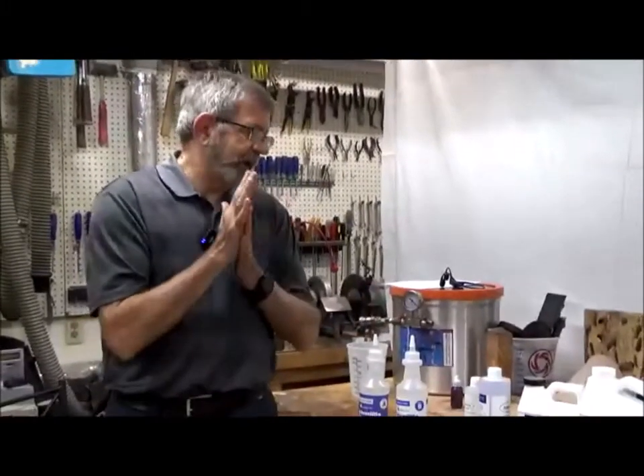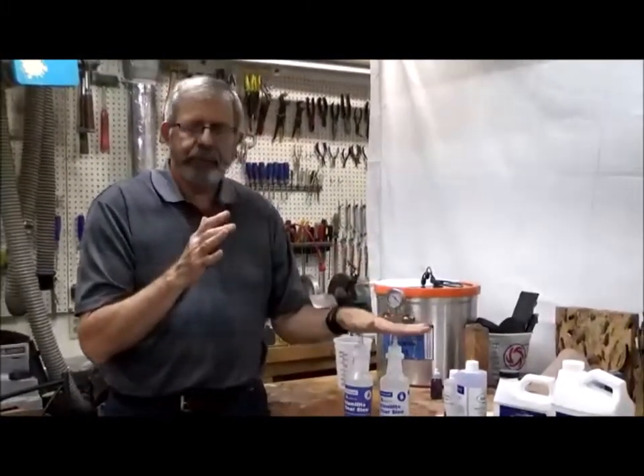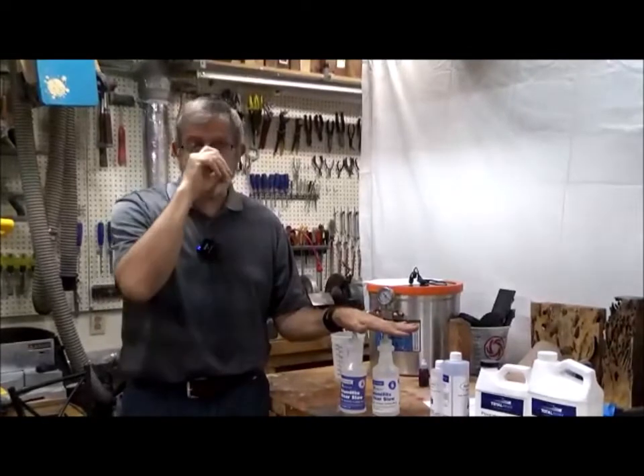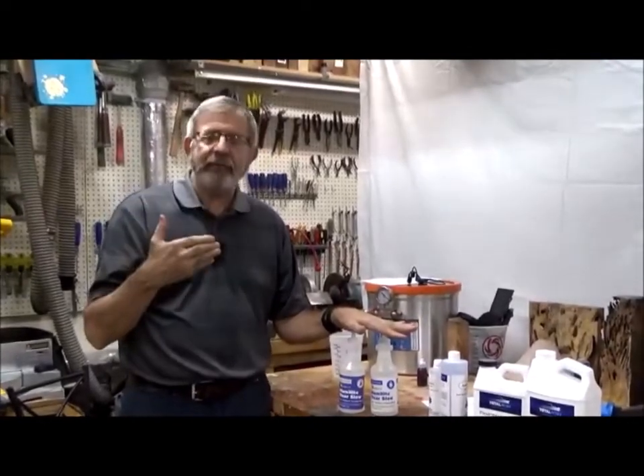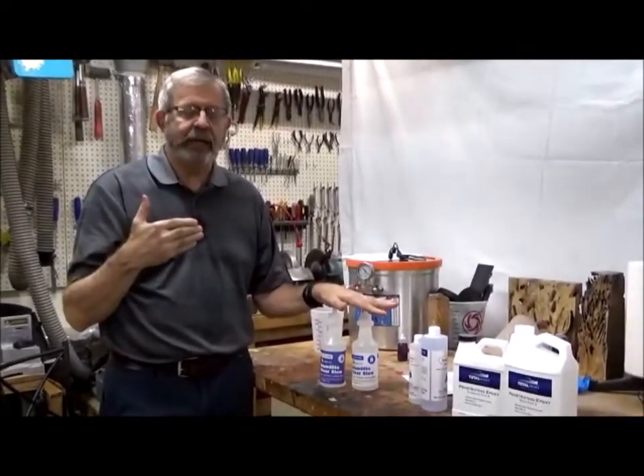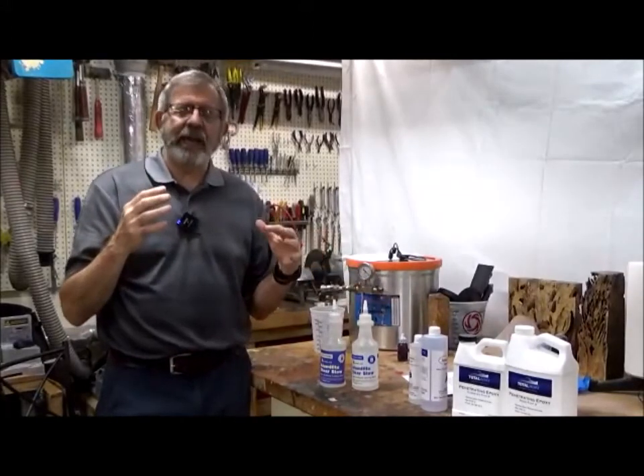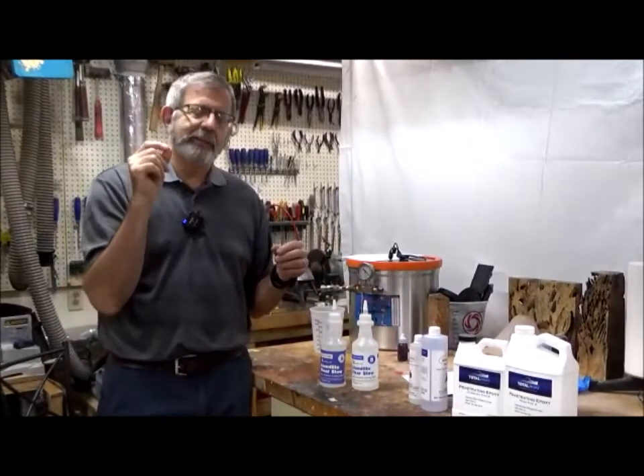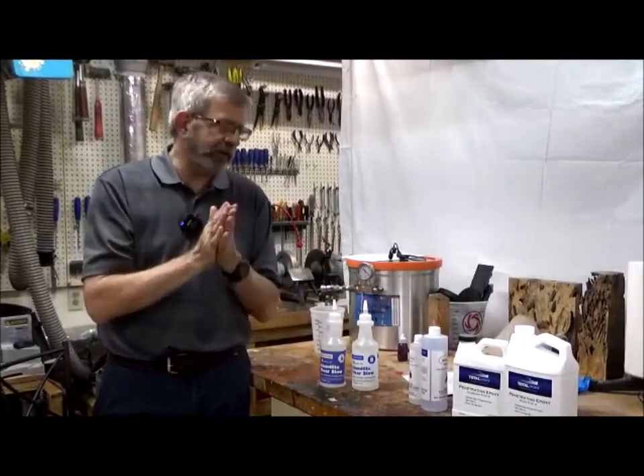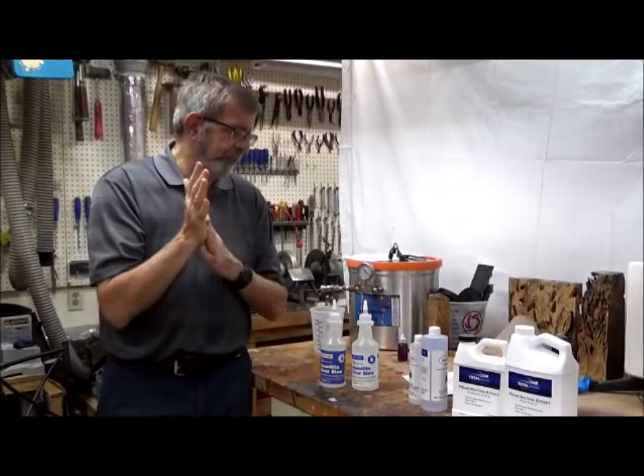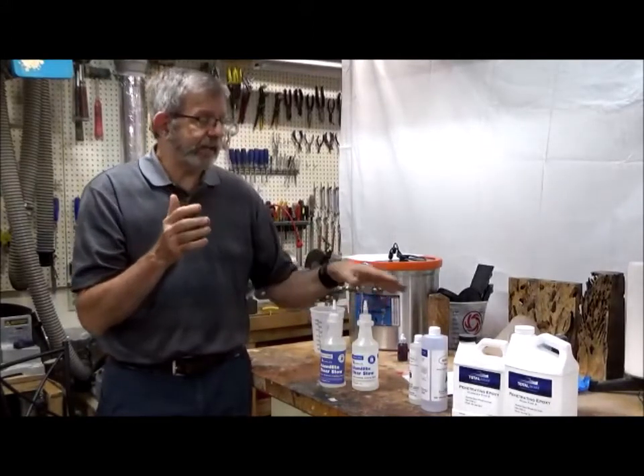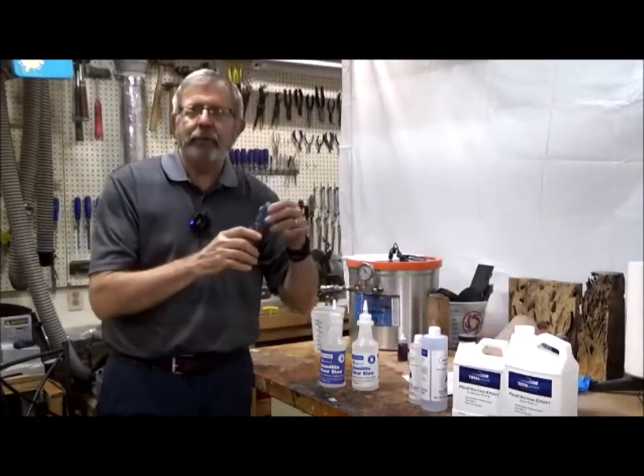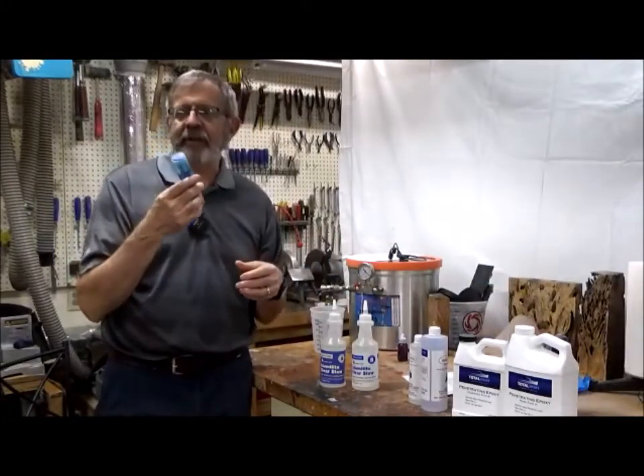That's the advantage of casting under pressure. But the polyurethane, because it does set so quickly, you have to use a pressure pot in order to get the air bubbles out. And it doesn't get the air bubbles out. What it does is the pressure pot makes them microscopic, so you can't see them. But what's nice is that I could cast a bottle opener blank in the morning and turn it that afternoon.